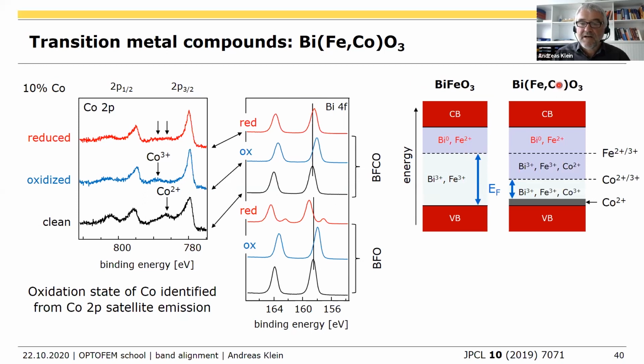If we add cobalt, the Fermi level can only vary in this range, at least after the oxidation of the sample, because here the cobalt is 3+. If you want to raise the Fermi level further, you first have to reduce the cobalt. So this doping can prevent the reduction of bismuth and iron, because of the confinement of the Fermi energy.